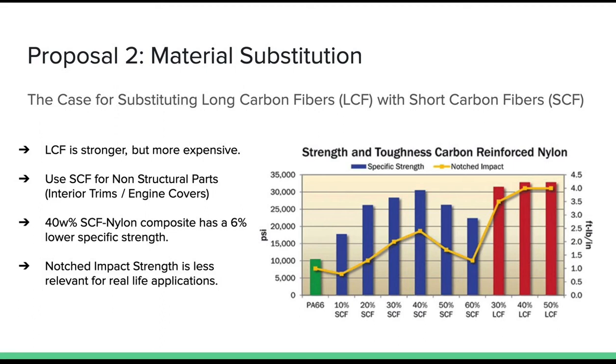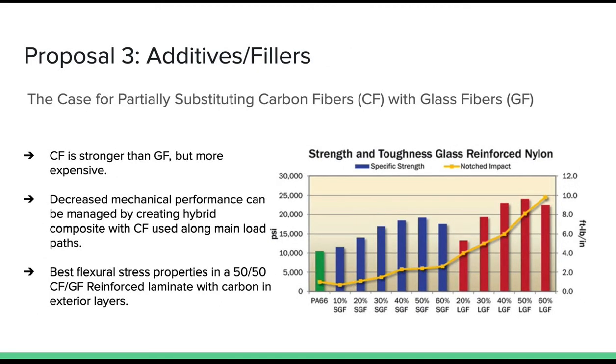Glass fiber is increasingly being used to manufacture high-volume automotive components to reduce weight and was easier than carbon fiber to adopt. And this takes us to our third proposal, which is using additives and fillers, this is the case of partially substituting carbon fibers with glass fibers. One method to decrease weight without excessive cost increase is to reinforce glass fiber composites with carbon fiber along the main load paths. These hybrid composite laminates are made by weaving an epoxy resin matrix with carbon and glass fibers.